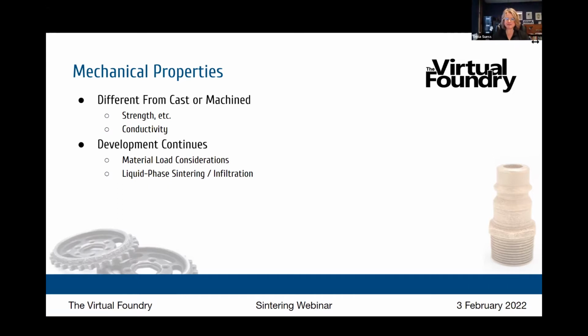And then when we get into the conductivity discussion, especially electrical conductivity, if we're thinking about copper, because those final parts are porous, they are going to have reduced electrical conductivity compared to a solid block of copper. We have a student's thesis paper on our website that did a careful analysis of the conductivity of our copper. Basically, we found that the electrical conductivity of the copper is dependent on two things. Number one, purity, but number two is density. So a highly porous part, say it's only 75% metal, filled with holes, sort of like a sponge, will conduct electricity at roughly 75% the rate of pure copper.